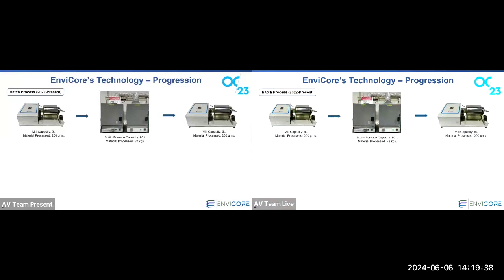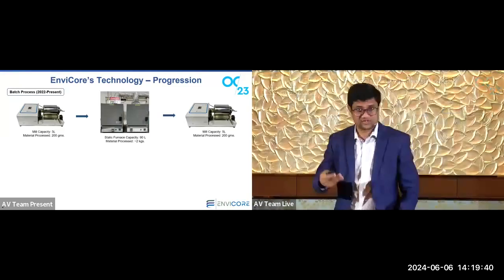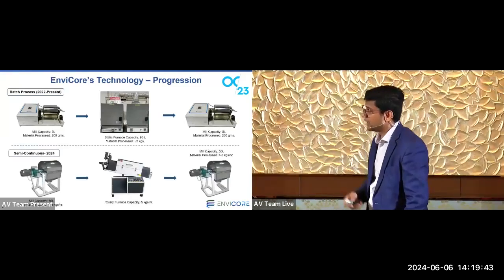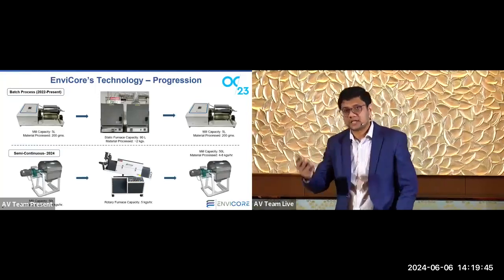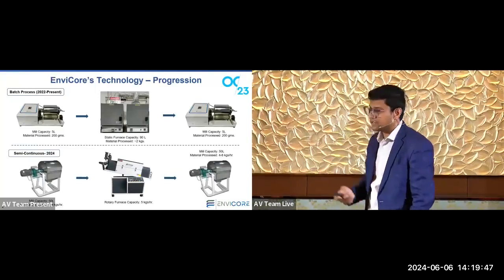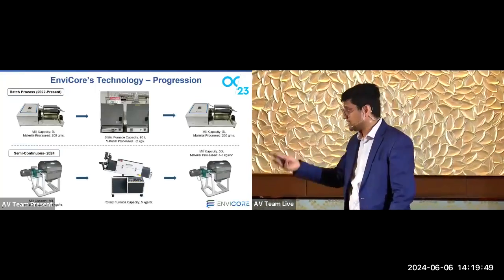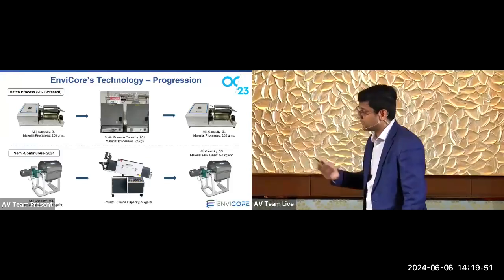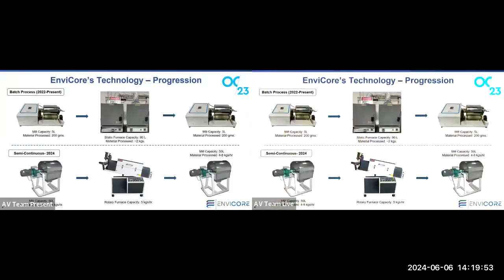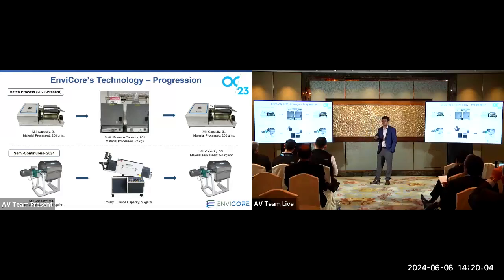But then we decided to scale up the process internally, just in our own warehouse. We were able to develop a semi-continuous operation that can take up to 8 kilograms of material per hour. And we have a dynamic furnace that can be continuously processing the material to achieve the activation, and that can do up to 5 kilograms an hour. And finally, the same capacity mill for our finish mill, if we are not doing any co-grinding.